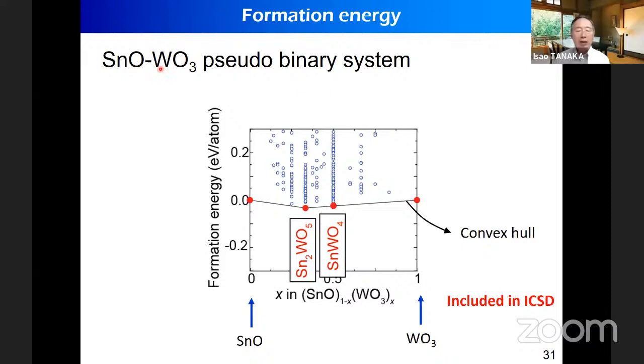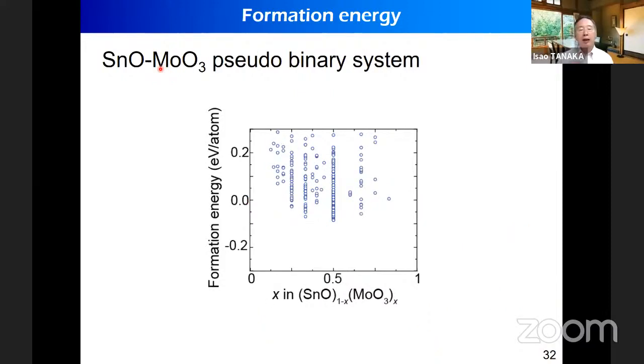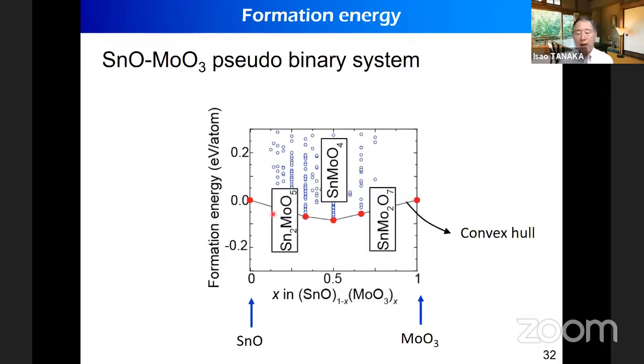If we change this tungsten to molybdenum, which is located just above the tungsten in the periodic table, then we made a similar plot and made a convex hull to find those compounds on the convex hull. And we also examined ICSD, and none of them were registered in ICSD. It means they are as yet unknown compounds. So it may suggest that there is a good chance to find a new compound.